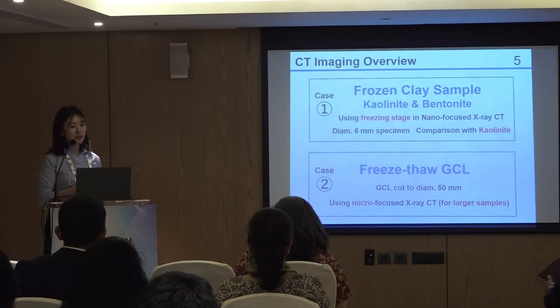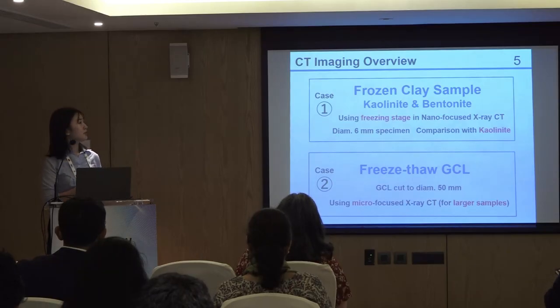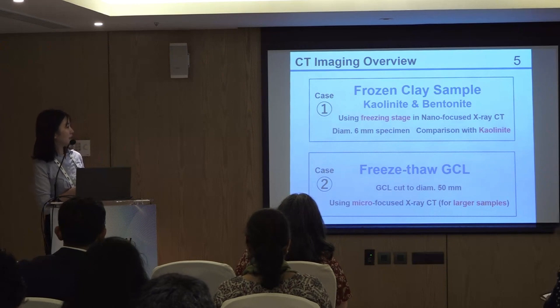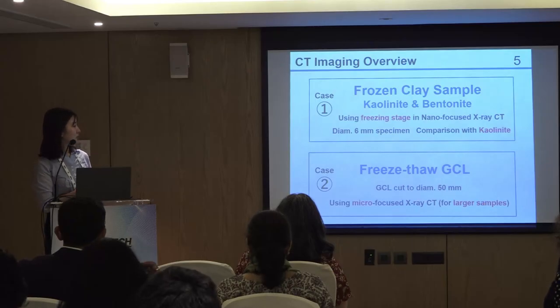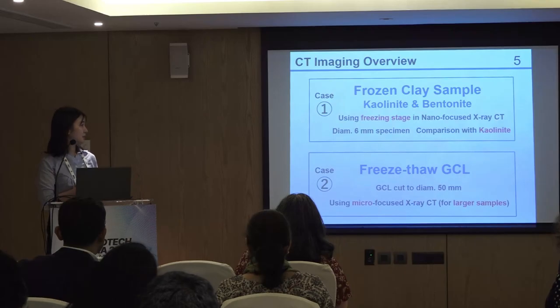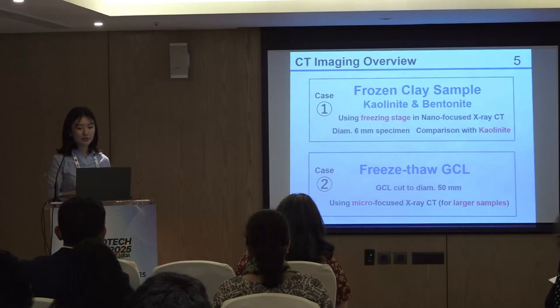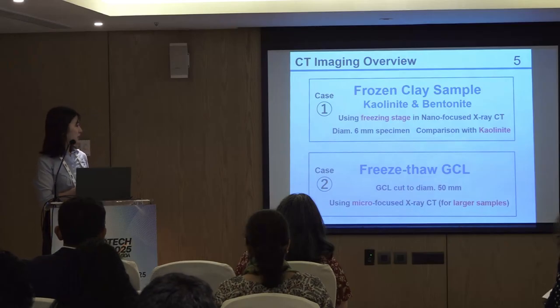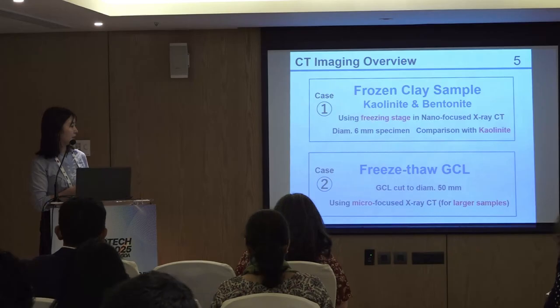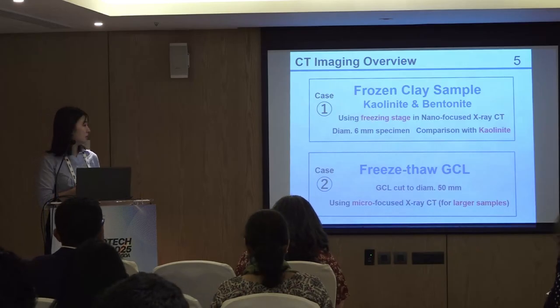In this study, we separately scanned a frozen clay sample and GCL under freeze-and-thaw cycles. First, for the frozen clay sample, we scanned kaolinite to clarify the freezing characteristics of bentonite. We used the freezing stage of the nano X-ray CT to scan the specimen with a diameter of 6 millimeters. Next, we scanned GCL under freeze-and-thaw cycles. Since GCL was cut into a disc with a diameter of 50 millimeters, we used micro-focused X-ray CT for the scanning.